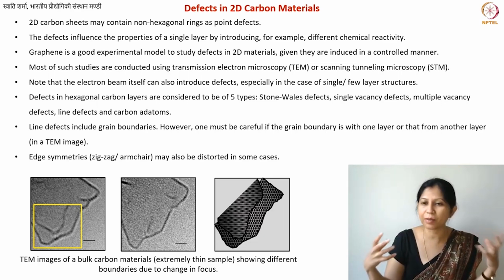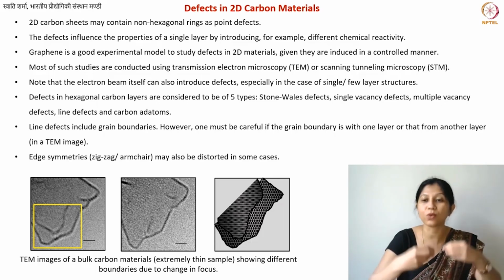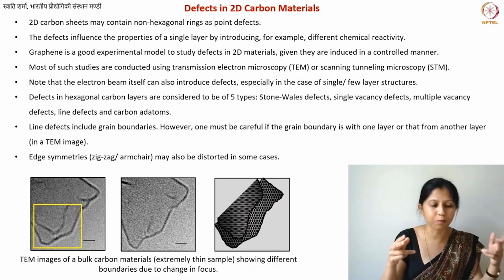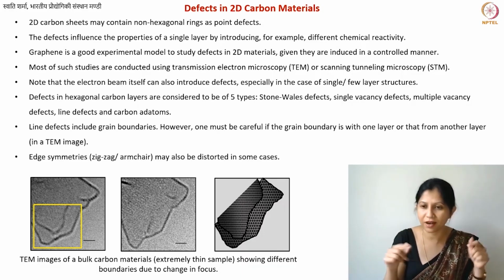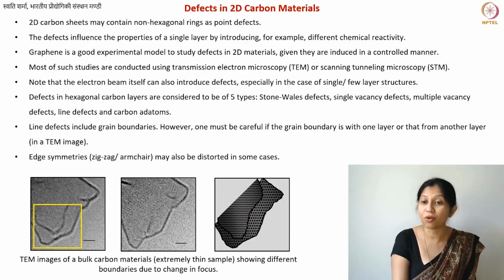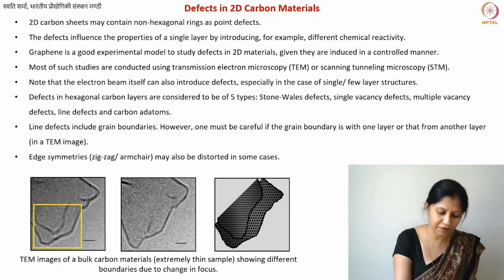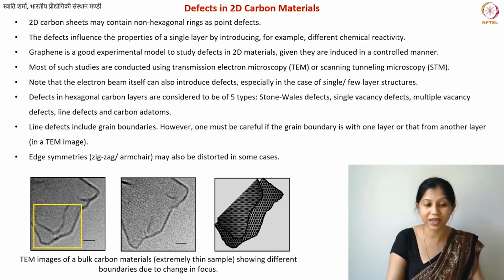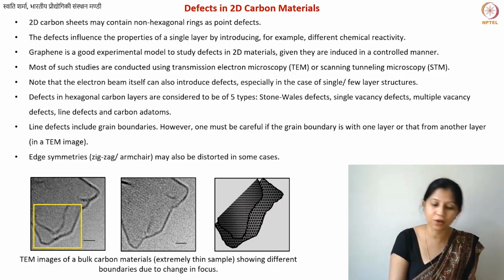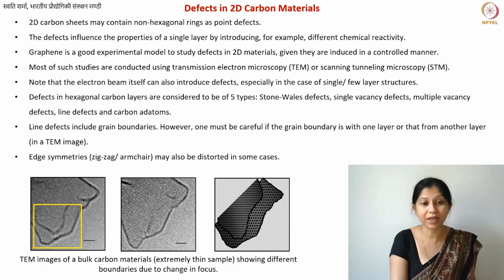At the edges you have a little bit of very strange structure. Sometimes one atom is just, like, rough edges. So they do not have any specific type of symmetry, but they have some other type of structure, which again makes them more chemically reactive. Already the edges of graphene have dangling bonds, because there is no termination, so to say. So you have dangling bonds there already, and sometimes if the structure is also not according to these two symmetric arrangements, in that case you can also have higher reactivity along the edges of graphene. So that can also be considered a defect.